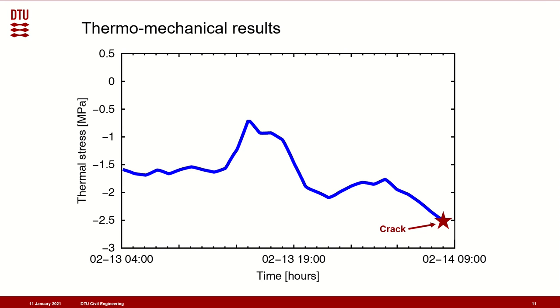Based on the presented mechanical model, the thermostresses were calculated for the period identified on the previous slide. Here represented is the chart with the time on the x-axis, specifically between the 13th February 4 am and the 14th February 9 am. The thermally induced stresses are placed on the y-axis, with tensile stresses taken as negative. It is considered that the asphalt material has a tensile strength of 2.5 MPa. Here is the evolution of the thermostresses for the calculated surface temperature. As can be seen, a crack would have occurred at approximately 8 am on February 14th.